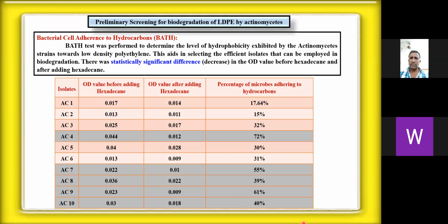Preliminary screening for biodegradation of LDPE by actinomyces: bacterial adherence to hydrocarbon test was performed to determine the level of hydrophobicity exhibited by actinomyces strains towards low density polyethylene. This aids in selecting the efficient isolate that can be employed in biodegradation. By seeing the table, AC4 showed a maximum percentage of adherence, hydrophobicity of 72%, followed by AC9, 61%, followed by AC7, 55%, AC10 at 40%, and AC8 at 39%.